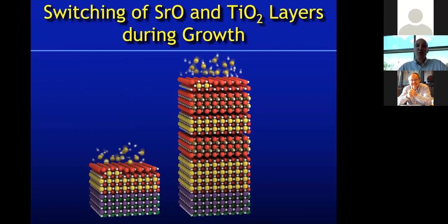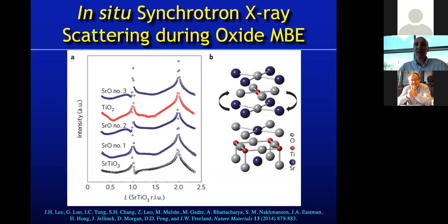that problem. So what we saw from our experiments here was if we have a surface that consists of a double strontium and we put titanium on top of it, the titanium goes through the strontium and forms strontium titanate. Okay, so it's energetically more stable to not have titanium on top of a double layer of strontium oxide, but to have a perovskite. Okay, and that's been shown from first principles calculations, not only in strontium titanate, but in many of the Ruddlesden-Popper series.